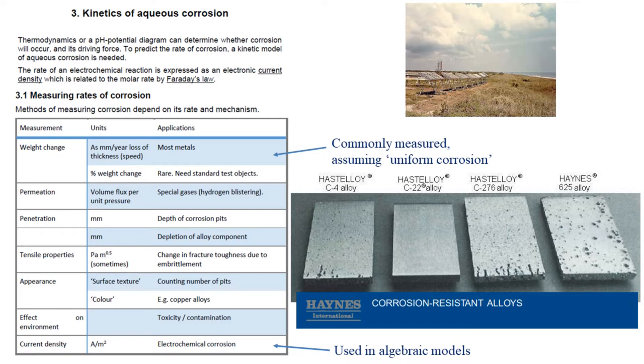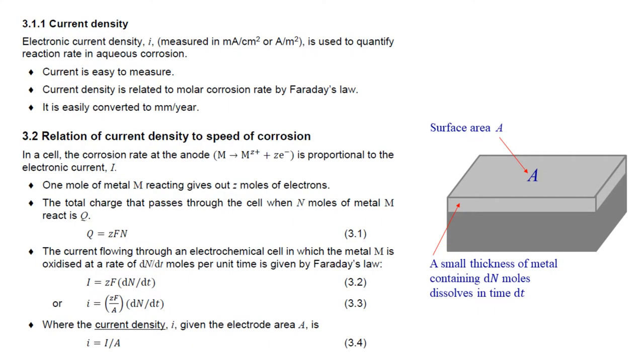Okay. On page 26, we start with a statement in section 3.1.1, which introduces the algebraic symbol small i, used for describing current density. Current density is used in electrochemistry to quantify the speed at which some electrochemical process happens in units of amps per meter squared. Let's just recall one of the reasons why current density is used in electrochemistry, which is that electronic current density is usually very easy to measure, and also it's not hard to translate it into corrosion speed in the more intuitive engineering terms of millimeters per year. We can do that translation using the Faraday relation in section 3.2.